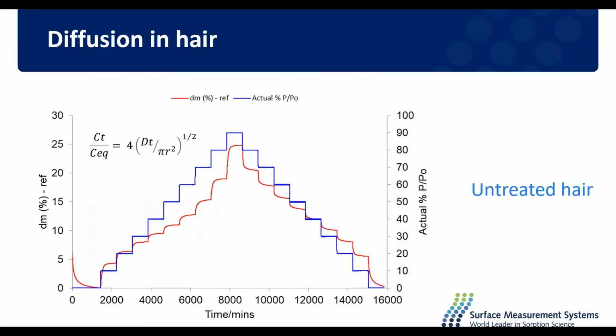So we also did some analysis on the diffusion coefficients. As with this kinetic data, that's one of the benefits. You can fit this data to a model, and here we just used Crank's model for diffusion as applied to a cylinder, where D is the diffusion coefficient, t is time, and r is our radius for our hair fibre. So we used an approximate radius for all the hair fibres here.